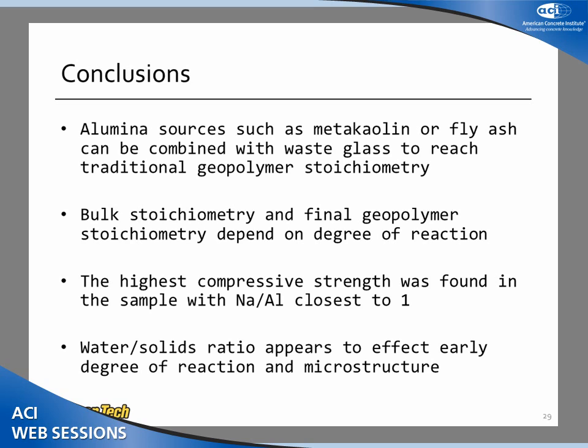For the highest compressive strength, I found that the sodium to alumina ratio was 1. I don't think this is conclusive that it is the reason, but it's definitely something I'm looking into more. I'm also doing some work on the water to solids ratio, because in the literature many people say it doesn't matter that much, but I wonder if that's why my 50% metakaolin literally fell apart. So that's about it.